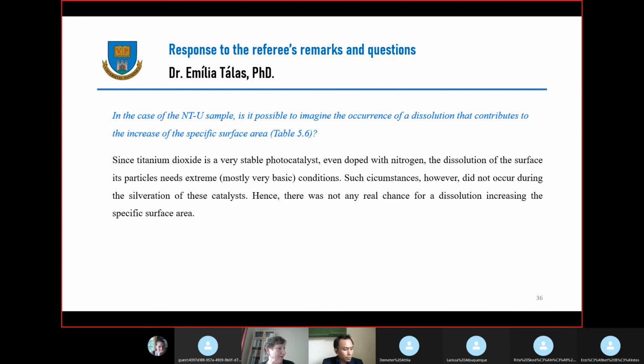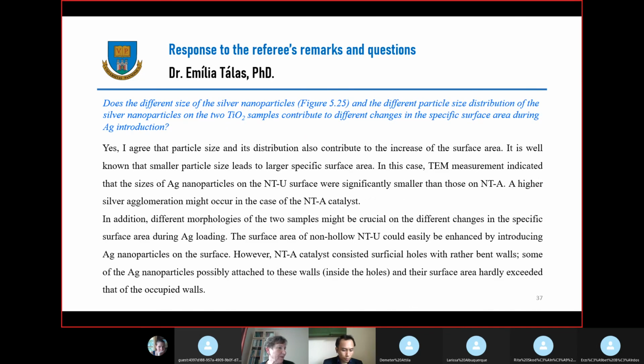Okay, thank you. And again with the specific surface area: do the different size of the silver nanoparticles and the different particle size distribution contribute to the different changes of the specific surface area? Yes, I agree that the particle size and also its distribution contribute to the increase of the specific surface area. It's well known that the smaller particle size leads to the larger specific surface area. In this case, the TEM measurement indicates that the size of the silver nanoparticle on the NTU was significantly smaller.